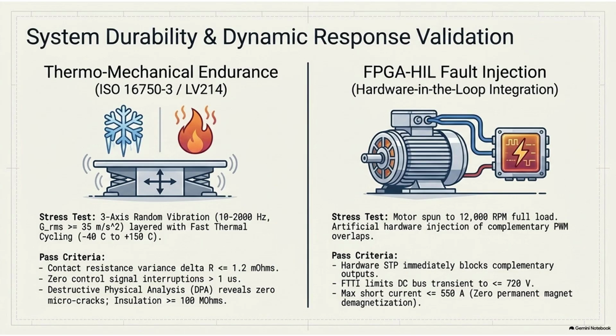How do you simulate a decade of bad roads? You accelerate the aging process through extreme violence. They take the inverter and bolt it rigidly to a multi-axis electrodynamic vibration table. They shake it with a frequency sweep ranging from 10 Hz up to 2,000 Hz, pulling a constant 35 meters per second squared of G-force. That is nearly 3.5 Gs of continuous, high-frequency, bone-rattling vibration.